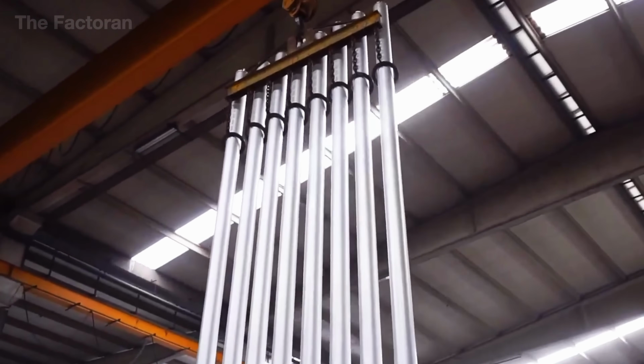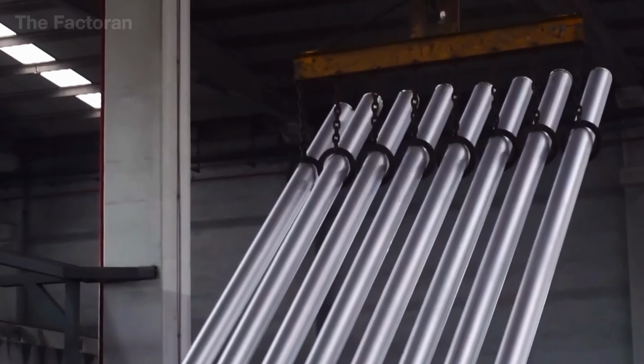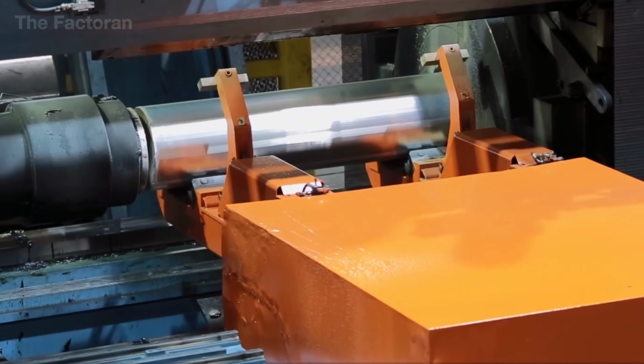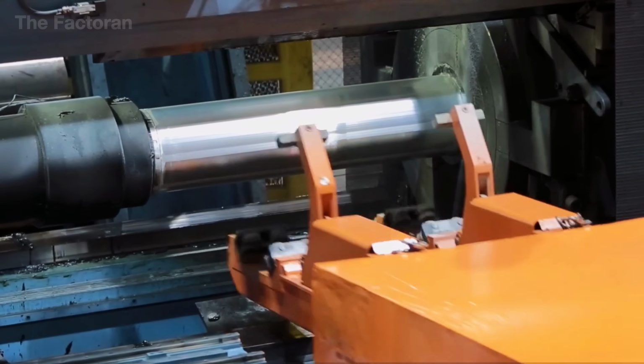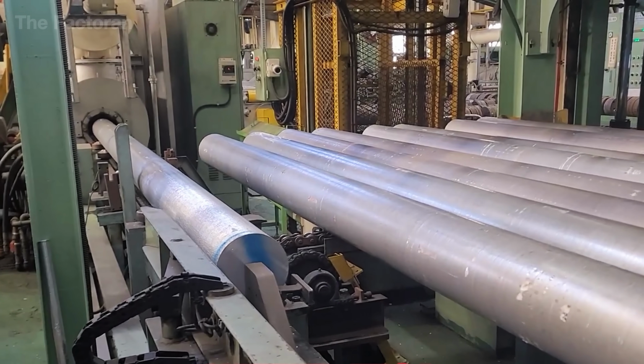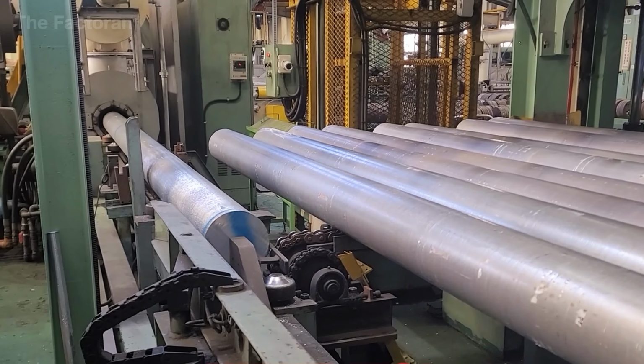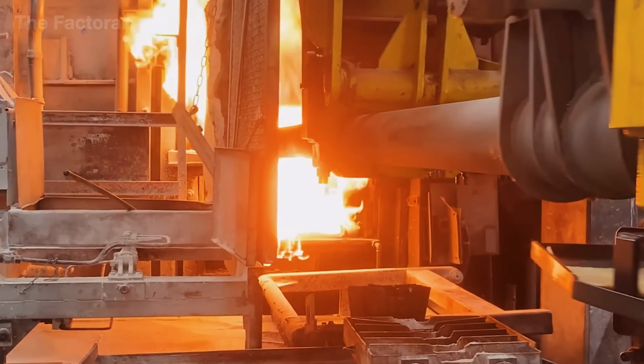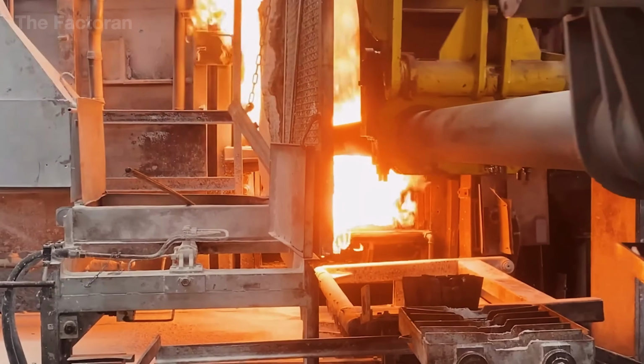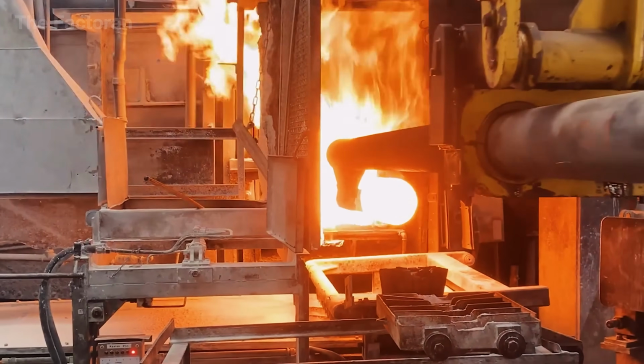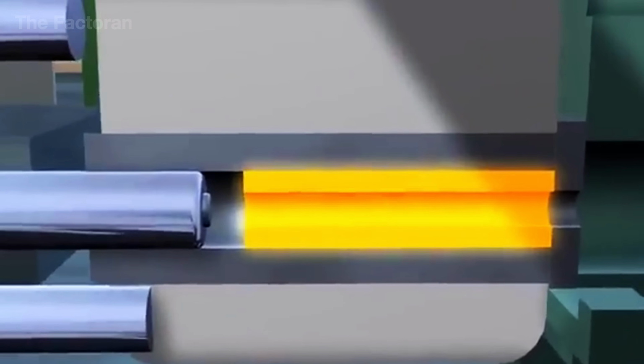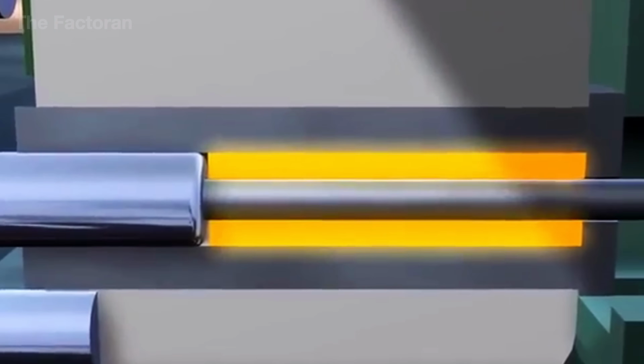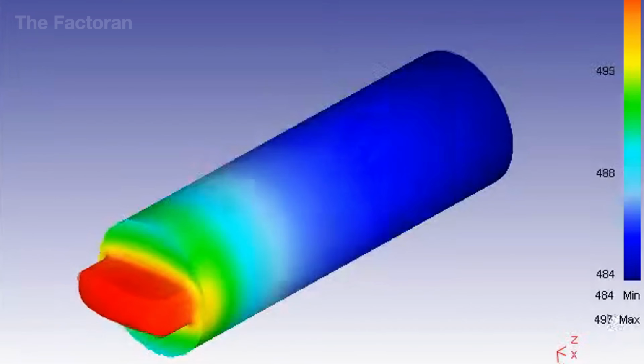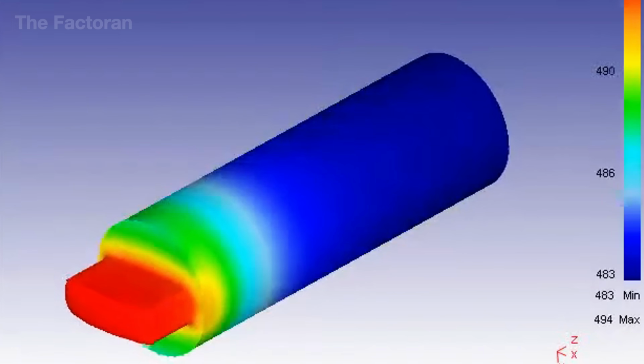Aluminum doesn't end its journey in the form of thin foil for packaging or food service. In the worlds of engineering and construction, it takes on another path: aluminum extrusion. Here, cylindrical billets are heated to about 842 to 932 degrees Fahrenheit to make them malleable while retaining structural strength. Under the immense force of a hydraulic press, the billet is pushed through a hardened steel die, precisely shaped to the desired profile.